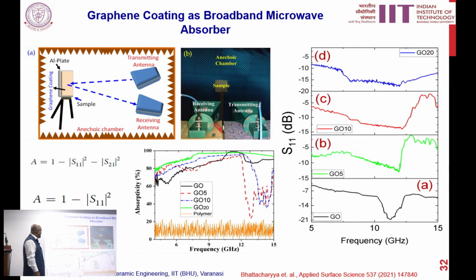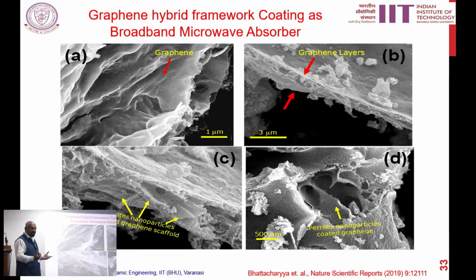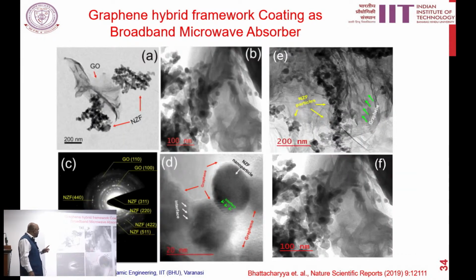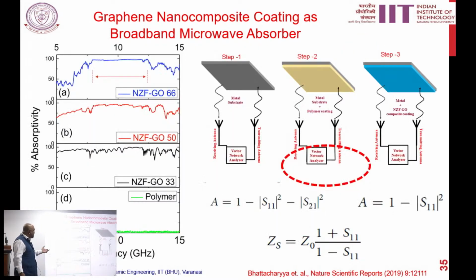So this is one of the features, and the second one is the hybrid framework. Now the terminology comes as hybrid. You see the SEM, scanning electron microscopy, a small magnetic nanoparticle being infused inside the graphene layers. You see the graphene layers, so they create a framework. That framework is more beautifully seen in this TEM image. You see each and every graphene layer is connected with small magnetic nanoparticles, and those magnetic nanoparticles basically create an interface, and that magnetodielectric interface is primarily responsible for absorbing those